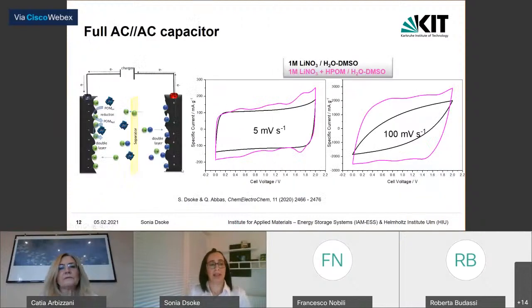After this, I built a supercapacitor by using activated carbon electrodes on both sides. And I prepared an electrolyte containing polyoxometalate and another one without polyoxometalate. And as you can see, in the case of pure lithium nitrate in water and DMSO, you can observe a typical double layer square box voltammetry, which you can see from the black curve. And when we have the polyoxometalate, you can see the superimposed multiple redox peaks. And when we go to higher scan rate from 5 to 100 millivolt per second, we can see that there is a very good retention of the shape of the cyclic voltammetry. That means that the polyoxometalate-based water and DMSO system is very good also for a supercapacitor, so to be used with high power devices.